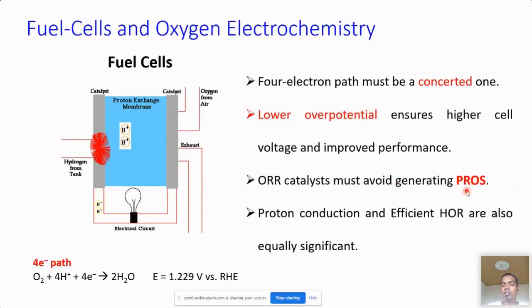These partially reduced oxygen species or potentially reactive oxygen species can lead to many other complications, including the destruction of electrode material, membrane, and many other things. So we should be very careful about this one. And beyond that, proton conduction through the membrane and the efficiency of hydrogen oxidation are also equally important in determining the fuel cell's efficiency.